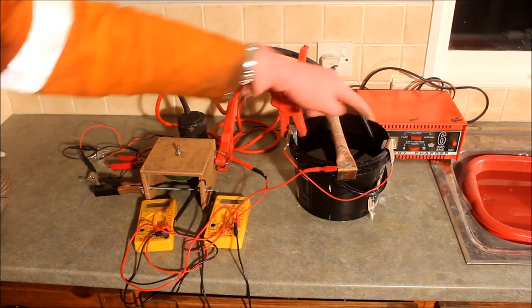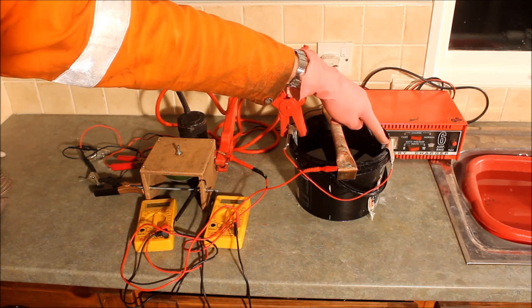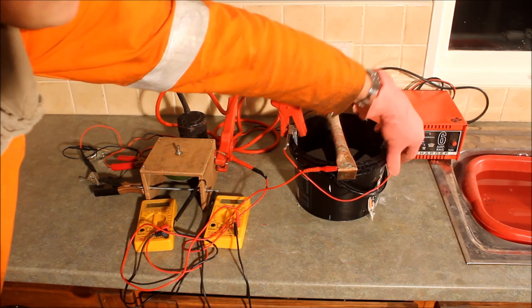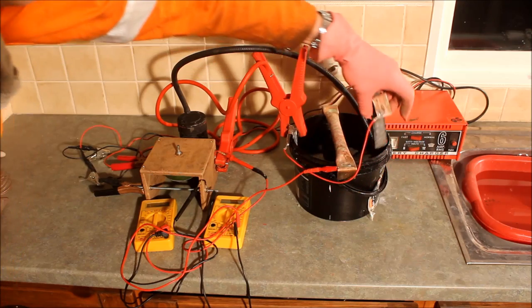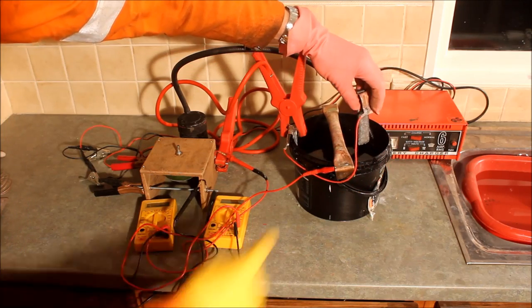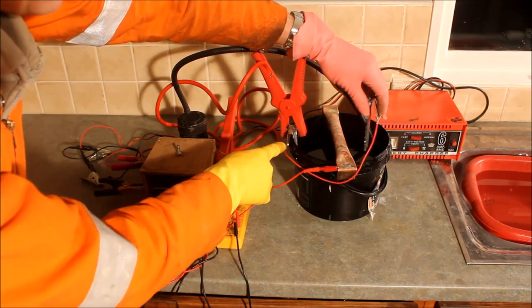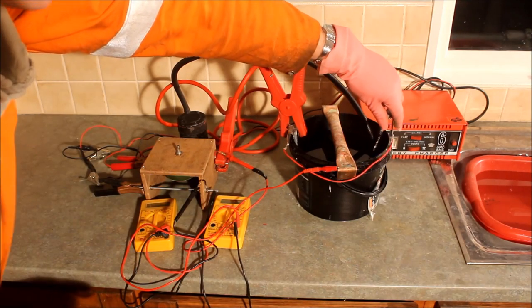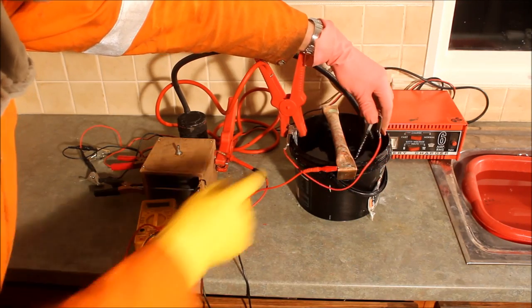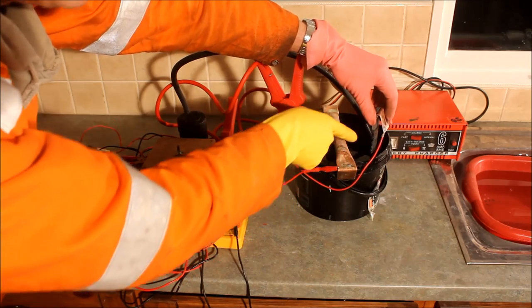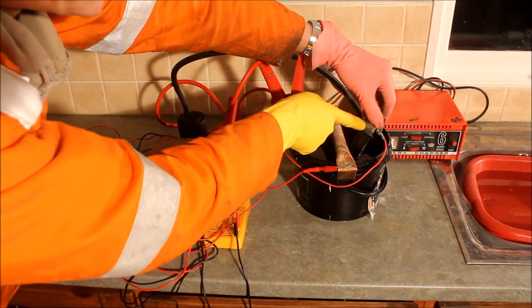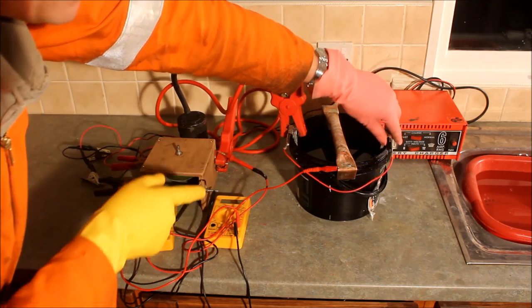So that and that are the anodes. They are pieces of zinc which are mounted to just a copper bracket, okay? And then they're wired together with this red wire. Okay, so that's the positive side of the tank, that's the anodes. Make sure that the copper and the copper wire stay out of the electrolyte. You only want the zinc of the anode sitting in the electrolyte.